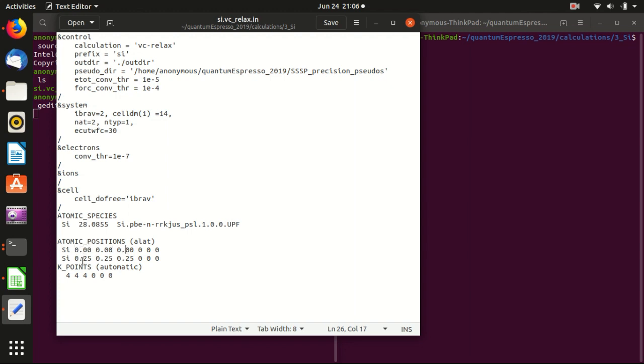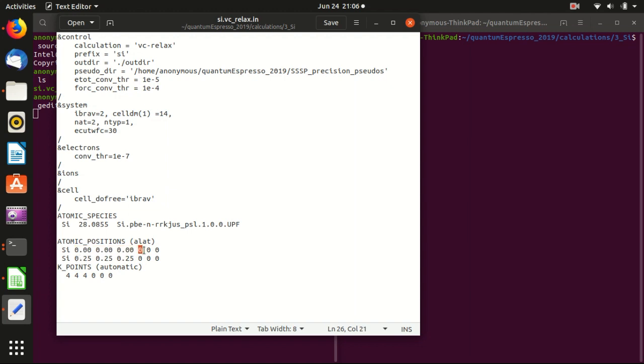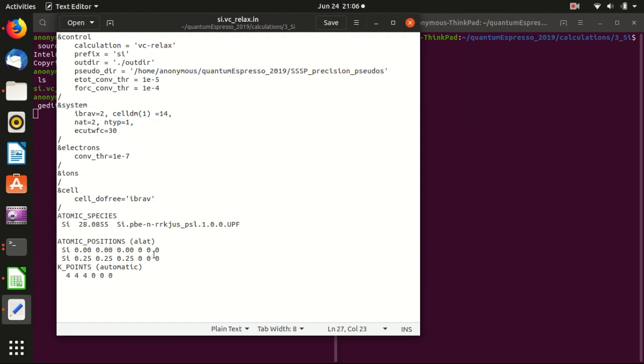So that's exactly what we can write here. The first silicon atom is 0, 0, 0. And the second silicon atom is shifted by one fourth of the FCC lattice. And what I write here, so basically the first three numbers are the actual positions of the atom. And then you can add another three numbers, basically either 0 or 1, to specify whether you allow that atom to move or not. So this means that we don't allow any coordinate of this atom to move. So it means that we only want to relax the unit cell, not the atoms itself.